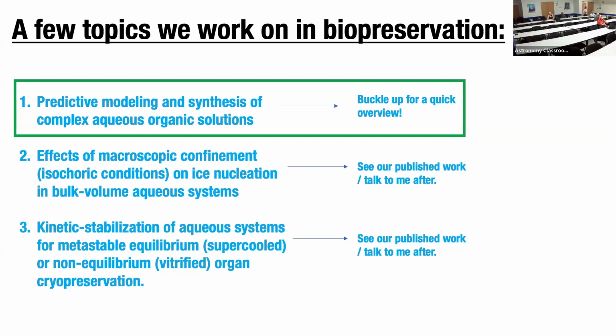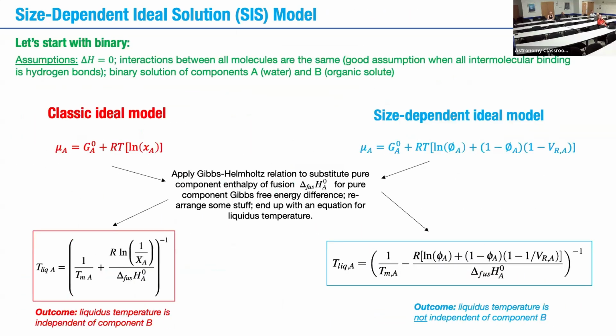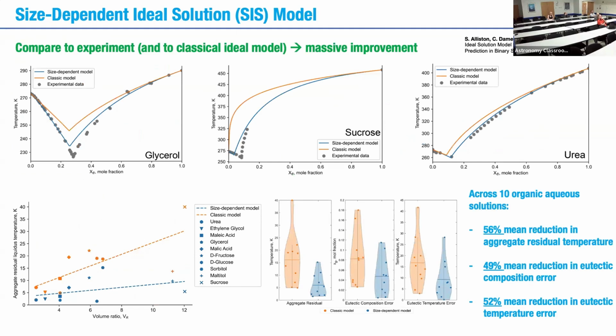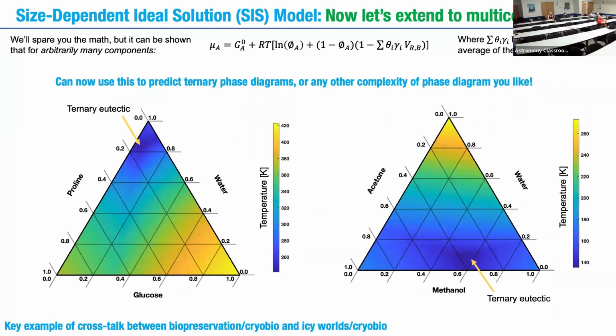But let me just do this. I'll do a tiny plug in case there's anyone watching who's interested in organics. The TLDR here is that we've developed some new ultra high throughput analytical thermodynamics approaches for predicting, based only on pure component data and using only classical thermo, the phase diagrams of aqueous organic systems, both in binary form and now also ternary phase diagrams, where we can isolate the ternary eutectic and it'll agree within a few degrees with experiments. And it's a generalizable technique that can go to n components. So it's a really interesting new modeling approach. So we're using this to design arbitrarily stable, biocompatible low temperature fluids.